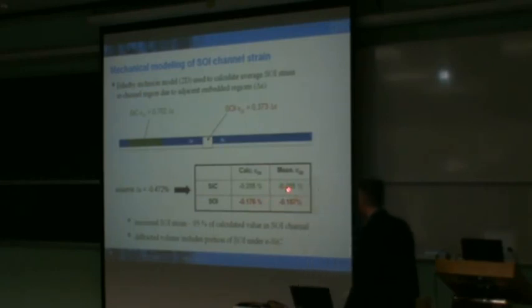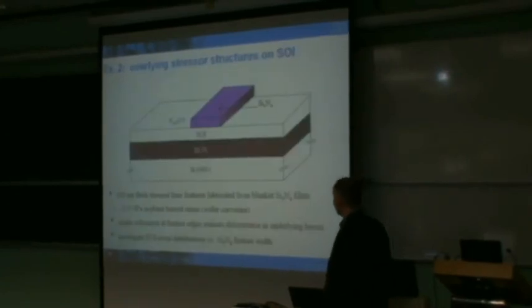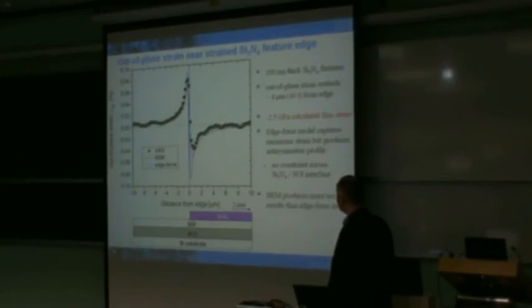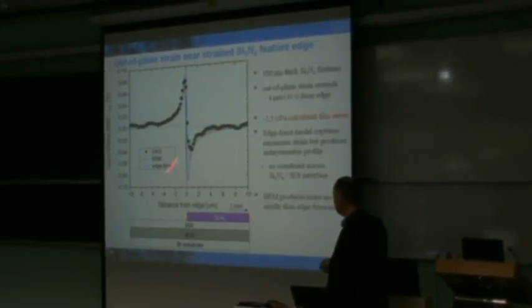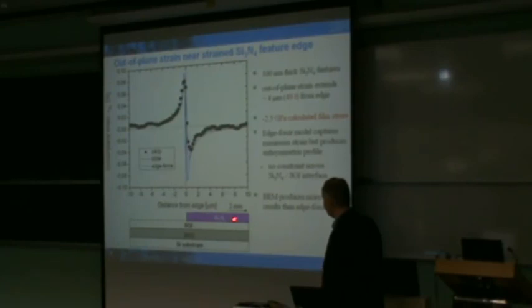For the case of looking at the silicon on insulator strain, we see a measured value about 95% of what we would expect from these models. And that's good considering the fact that the real device has a gate on top of it, and that's not included in the model. So clearly this is appropriate for at least looking at these sorts of structures. The second case that I won't go through, except just to show the results that we can get, is again by mapping the strain that's generated underneath these stressor structures, we can get a very nice map of the response. And the fact that, again, by the type of model that's used, we can actually get a reasonable prediction.